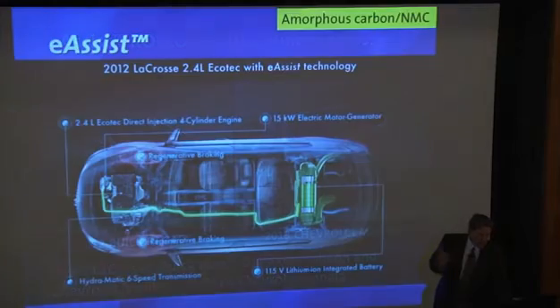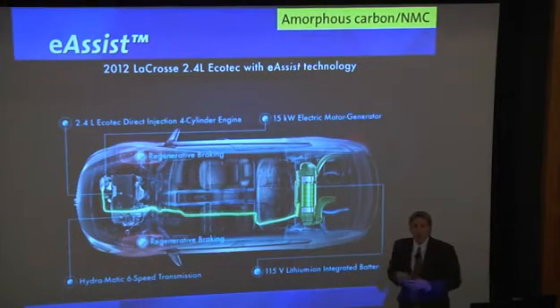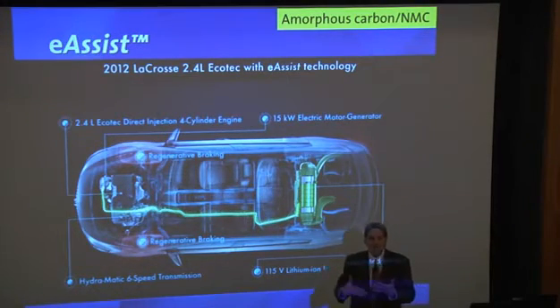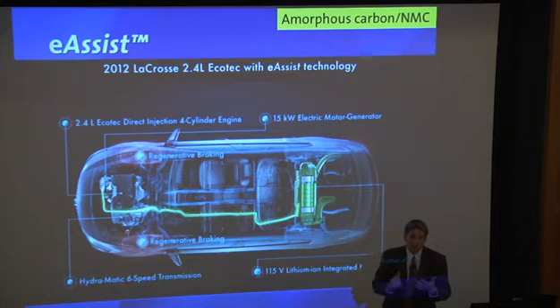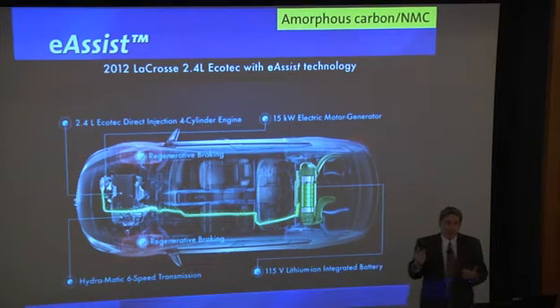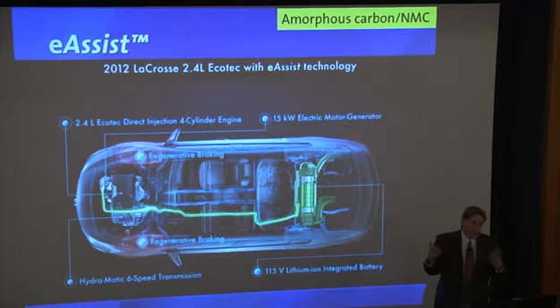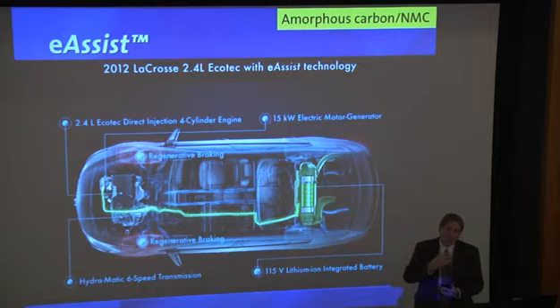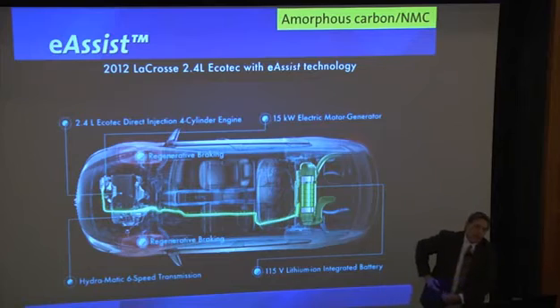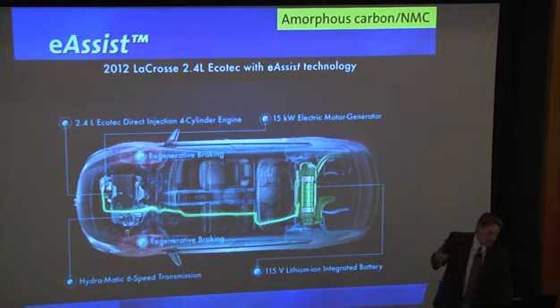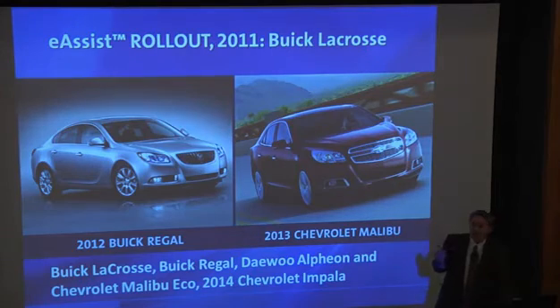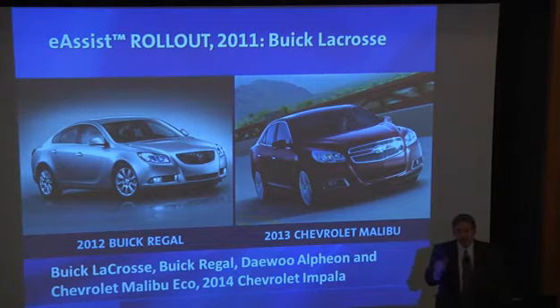So I should back up. That has an amorphous carbon. Amorphous carbon is very good for high-rate lithiation and delithiation compared to, say, graphite, the well-ordered carbons. And so in hybrids, where you're going after power, you typically see amorphous carbon, whereas in high-energy systems, I'll show, we typically use graphite electrodes. So the e-assist is coming out mainstream.